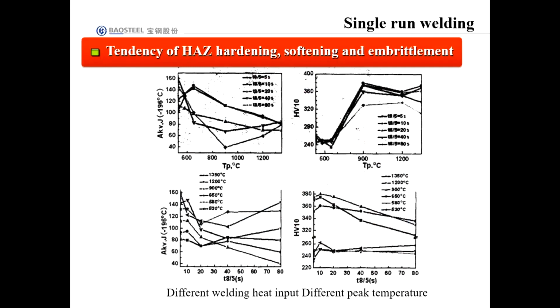This slide shows an example of single-run welding, which means that only one welding thermal cycle is applied to samples. We can see the tendency of hardening, softening, and embrittlement of steel's heat-affected zone. Hardening and softening tendencies are mainly reflected by hardness tests, while embrittlement property is mainly reflected by the impact toughness test.